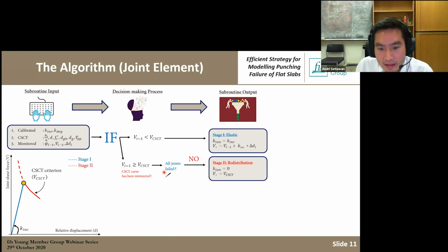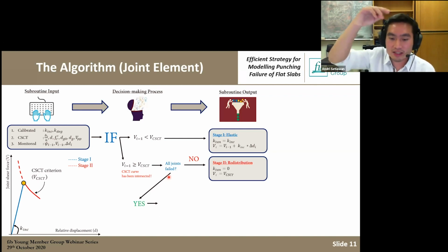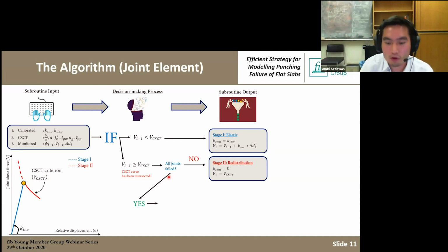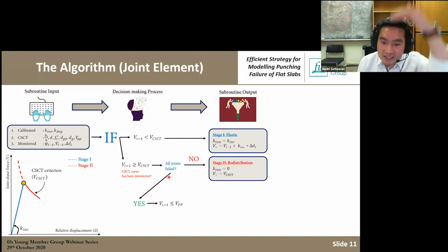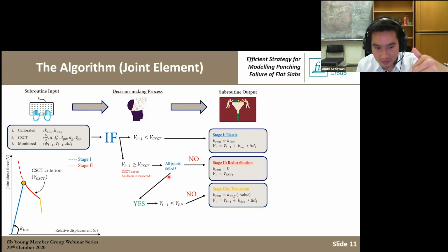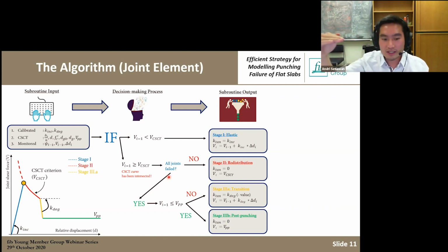Now, if all joints have failed, so the shear redistribution has completely finished and all the joints have been exhausted, we trigger the transition from global punching to the post-punching stage. The question is whether the remaining resistance is still larger than the post-punching resistance. If it's still larger, we have a drop from the global to the post-punching resistance. And then finally, we have a plateau, which represents the contribution from the integrity reinforcement.